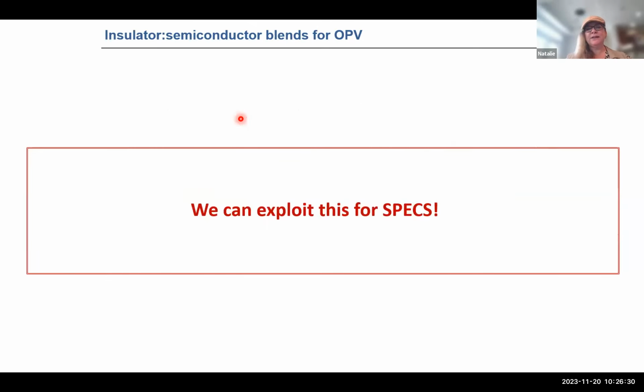So going now to, so I really think we can exploit this, hopefully, for specs, because I have to highlight here we really have extreme amounts of the insulator, but what we often use is other insulators like polystyrene of very high molecular weight. Very high molecular weight means like 1 million gram per mole up to 20 million gram per mole. And then you only need to add about 1 to 5 weight% with respect to your active material, not the solvent. And you have robustness, for instance, but in many cases you also get the benefit of stability with respect to charge trapping.